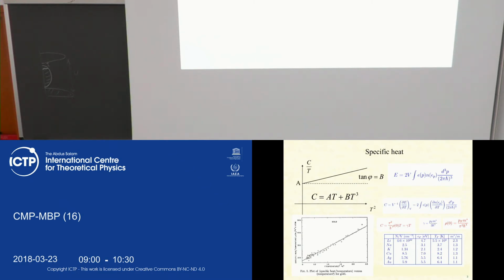So this is what I said, and this slide I already showed you when we discussed the fermions. A typical measurement of specific heat gives a plot of specific heat divided by temperature as a function of T squared. So A gives you the coefficient of the electronic contribution, which is proportional to the mass of the carriers, and coefficient B, the slope of this curve, gives you information about the phonon contribution. The Sommerfeld constant, for a three-dimensional metal, for example, is proportional to the mass of the carriers, and the mass of the carriers is extracted from the specific heat measurement, and the Fermi energy is given in this table.